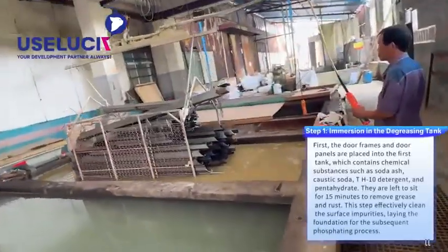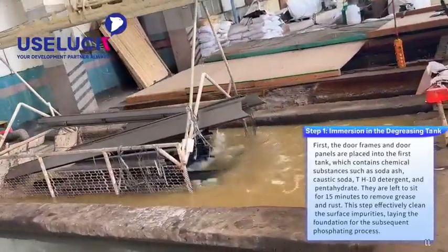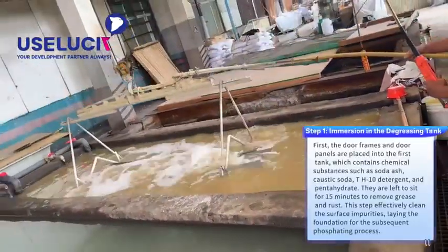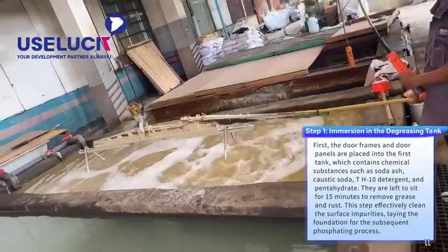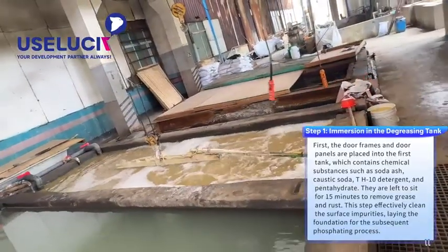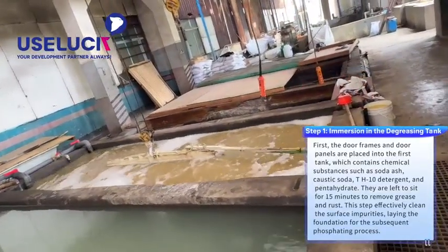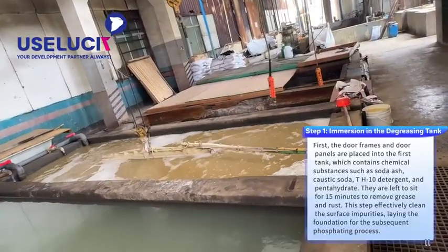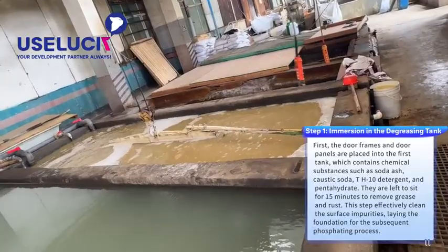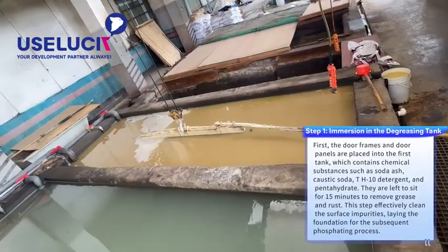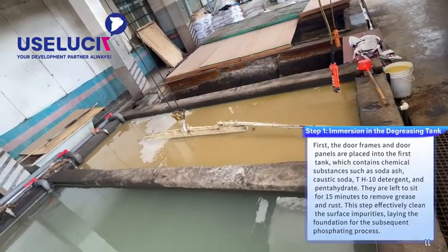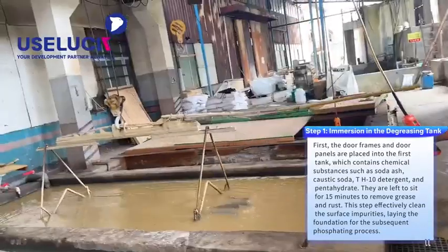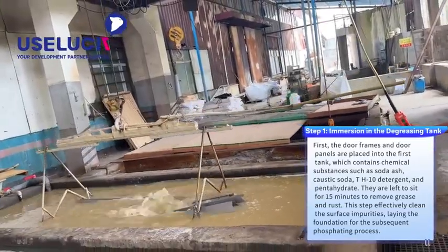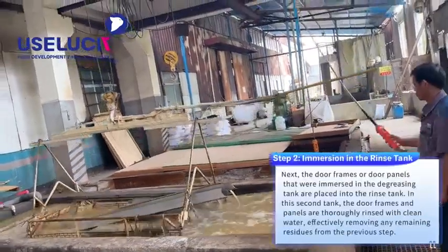Step 1. Immersion in the degreasing tank. First, the door frames and door panels are placed into the first tank, which contains chemical substances such as soda ash, caustic soda, TH10 detergent, and pentahydrate. They are left to sit for 15 minutes to remove grease and rust. This step effectively cleans the surface impurities, laying the foundation for the subsequent phosphating process.